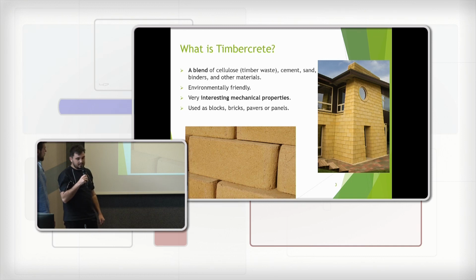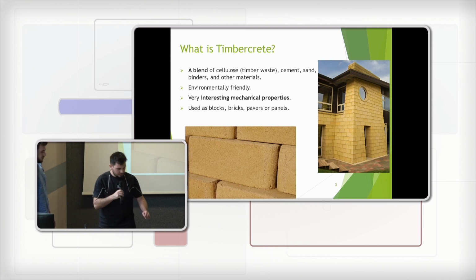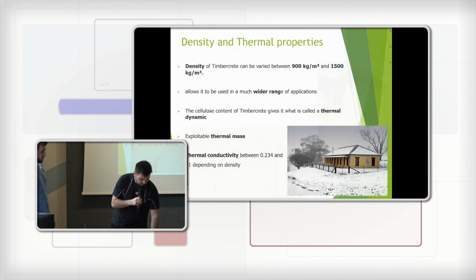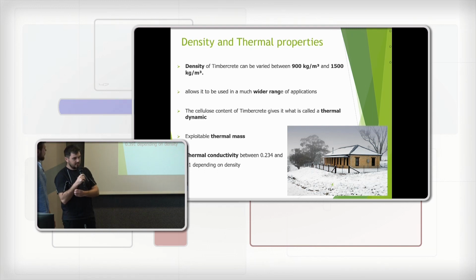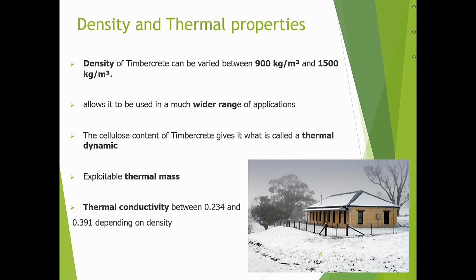We can ask ourselves what it is made of to have such good properties, but in reality it's really simple, because timbercrete is just a blend of cellulose, cement, sand, binders, and some other materials. So now I will present the properties of timbercrete. One of the most interesting properties is the density and the matrix of timbercrete. The density of timbercrete can be varied between 900 kilograms per cubic meter and 1,500 kilograms per cubic meter. So it allows it to be used in a really wide range of applications and to meet different construction needs.